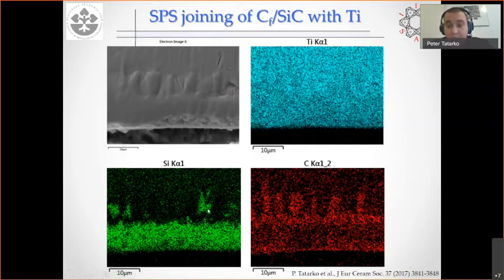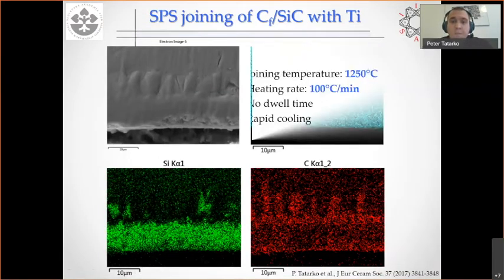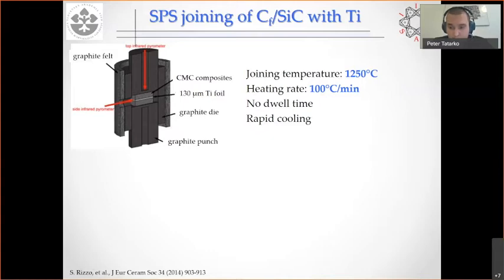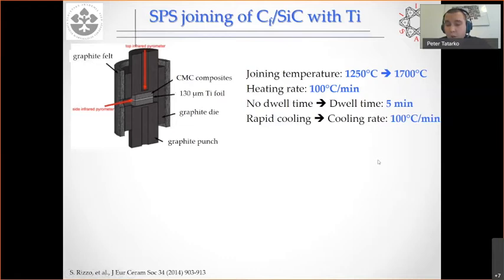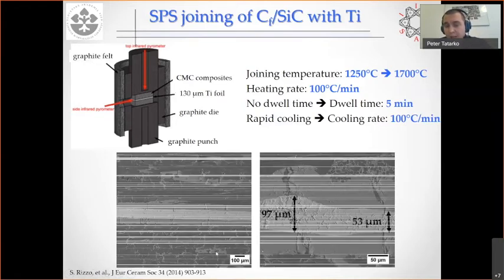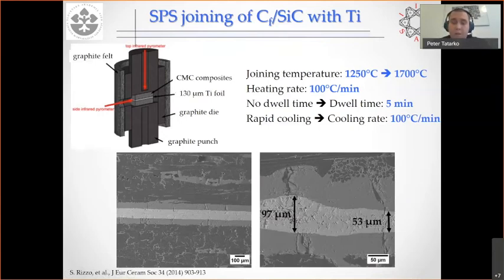titanium silicide. If you remember, for the flash joint process, the interface was clear, no diffusion, or let's say, I wouldn't call it no diffusion, but let's call it minimal diffusion, not enough to form additional phases. So if we wanted to get a similar joint using the standard SPS process, we had to increase the temperature to 1700, and we also had to apply some dwell time, and we also applied a cooling rate of 100 degrees C a minute. When we modify the standard SPS process, in that case, we got a joint. So you see no delamination, and we could test this joint.